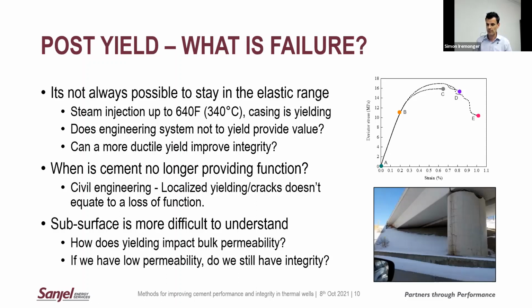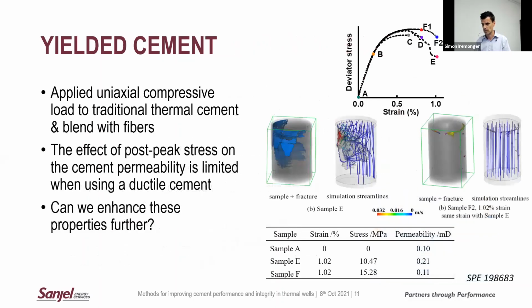So, what tools do we have for trying to understand how yielding might change integrity? And if you're thinking of integrity, really it's about isolation, and I think that comes down to permeability. So we can prove maybe that we still have low permeability. Do we still have integrity? And that was something we really wanted to look at. So taking a similar approach to the previous presenters, we're applying different axial loads to cement and then imaging them with micro CT, looking at the microstructure, the potential communication pathways, and modeling fluid flow through that. So we're comparing a conventional cement and again a cement with a fiber additive.